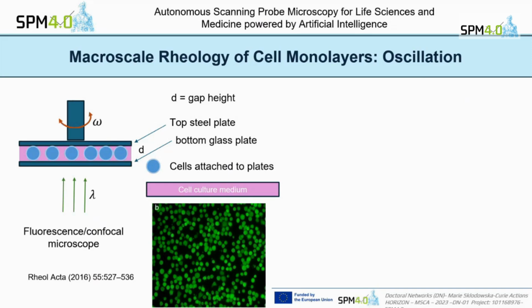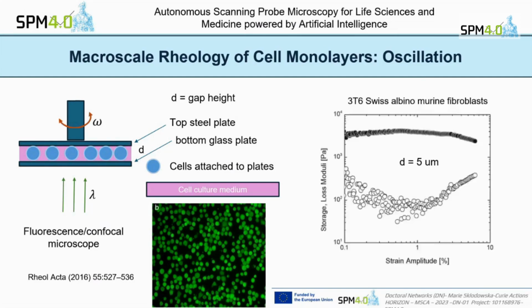So here you can see labeled adhered cells, and they are in the culture medium, and we perform the amplitude sweep measurement. So we oscillate with the constant frequency, but we change the deformation. So we increase the amplitude of the deformation in time.